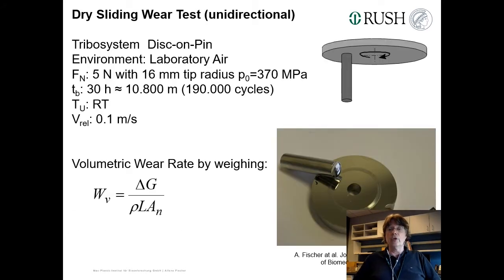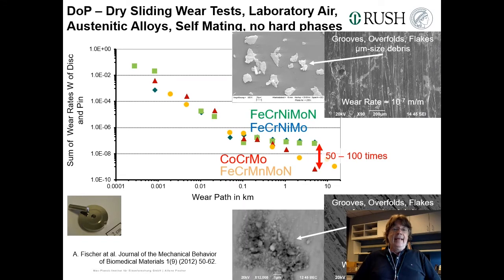And then you run a pin-on-disc test, and we wanted to make sure that all the wear particles just fall out. Then you get a certain running in. This is the sum of the wear of the pin and the disc. You remember, you have to analyze both bodies in such a system. The tests were run in dry air. There was absolutely no lubrication. So you get a running in, and then you come to steady state. And in steady state, the two steels more or less showed 50 to 100 times bigger wear rates than the cobalt chrome molybdenum alloy, as well as the high nitrogen steel. And the difference we could see on the surface is that you have a lot of grooves here, which certainly point to abrasion, but it's not micro-cutting, it's micro-plowing, meaning you generate grooves mainly just by plastic deformation.